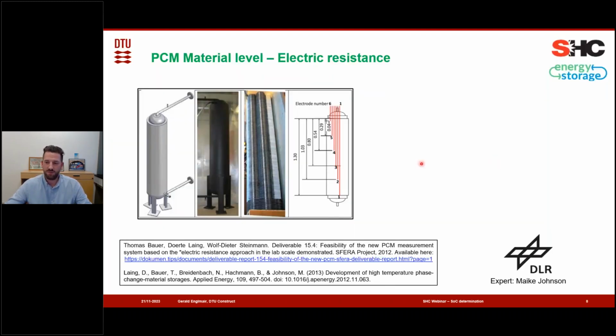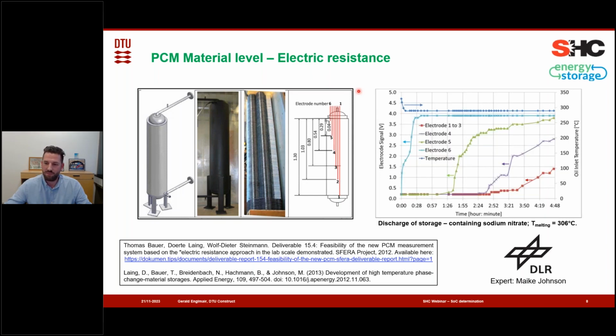First example is from the German Aerospace Research Center. It's a storage pilot for sodium nitrate for high temperature storage. And here we have an example where we have discharge at 290 degrees constantly. The melting temperature of the phase change material inside is 306 degrees.